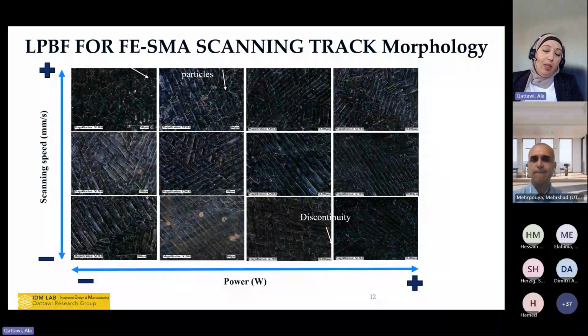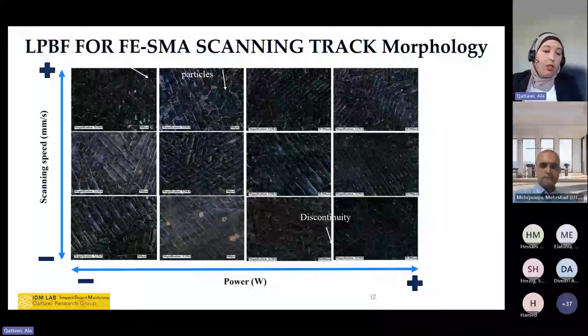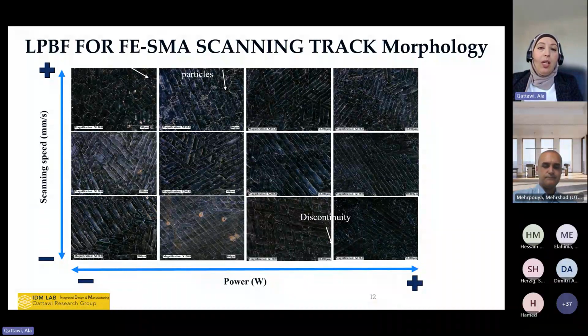In this recipe that we're producing, we also looked at the scanning track morphology. The scanning track morphology looks at how the scanning procedure melts and fuses the powder together. You can see with the different scanning strategies and different scanning speeds and power, there are also some defects and discontinuities that can be produced. And all this information that we get from the iron shape memory alloy may be correct for this certain alloy system or its variation.